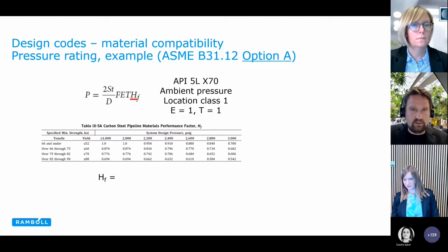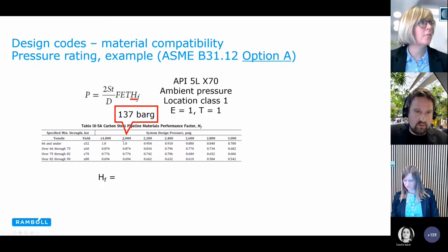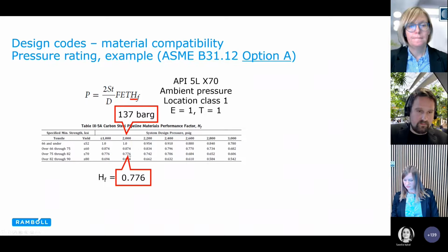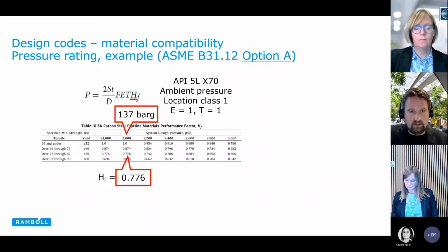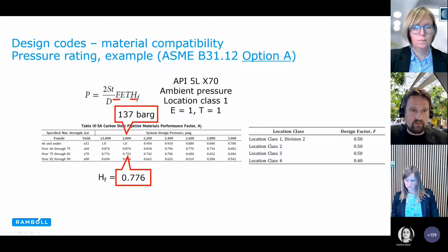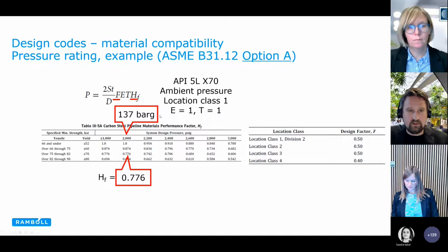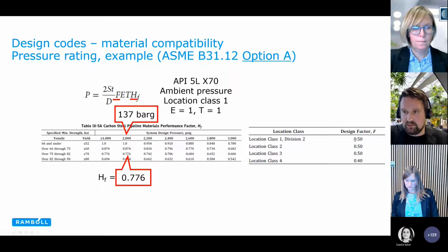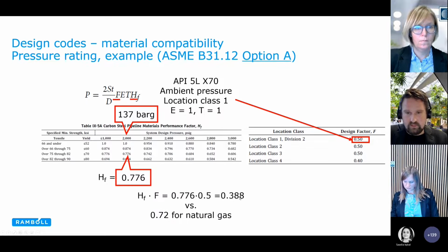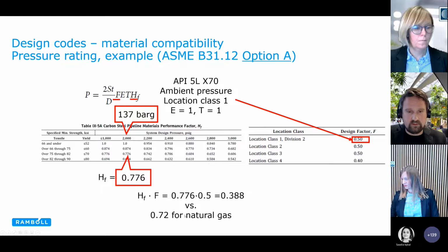So we go into a table in ASME B31.12 and look up our material performance factor, Hf, and let's just say we stay below 137 bar and we are working with X70, so here it is. We should select Hf as 0.776. And then we have another safety factor, F, the design factor, which for natural gas pipelines for location class 1 would be 0.72, but here we are limited to 0.5, so we multiply the two together and we get 0.388, multiplied to our allowable pressure, which should be compared to 0.72 for natural gas.